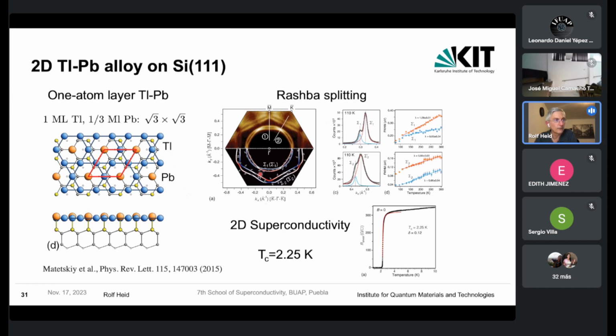And they have also been measuring different types of electronic states and their corresponding coupling, which they show depends on the band itself, but also on the bands with different spin momenta. Namely, they have also observed a nice Rashba splitting of the bands due to the existence of strong spin-orbit interaction coming from lead and from thallium. And this system is also superconducting with a transition temperature of 2.25 Kelvin. So even higher than the one seen for the pure lead case.